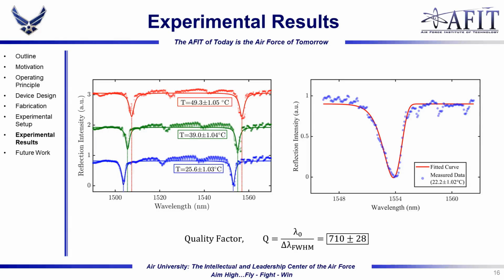This shape has been observed in the literature before and may be caused by the scanning speed of the laser or a phase shift introduced by a metal coating near the limited numerical aperture of an optical fiber. While further investigation is needed to fully understand this asymmetry, we fit a version of the skewed Cauchy distribution to 200 points around each dip, which captured the shape of the resonance feature fairly accurately.